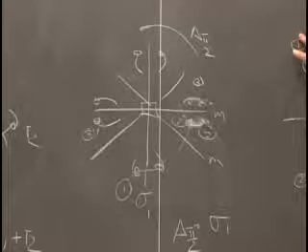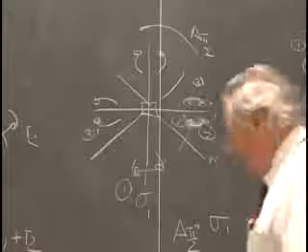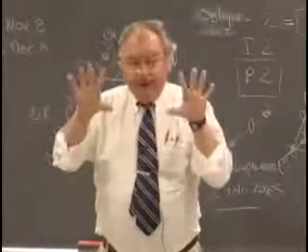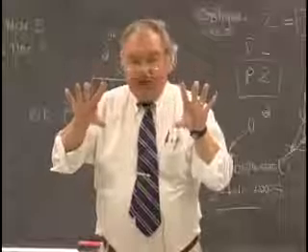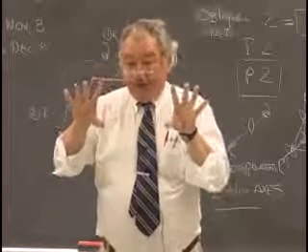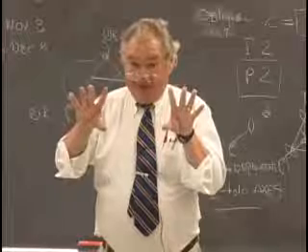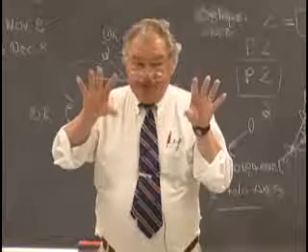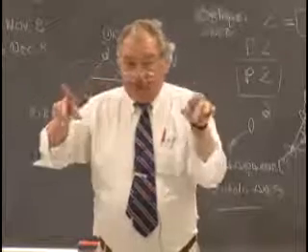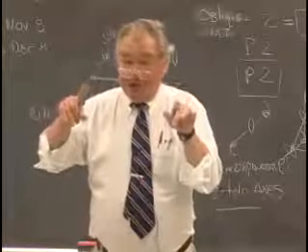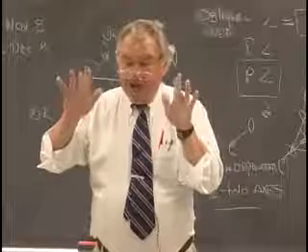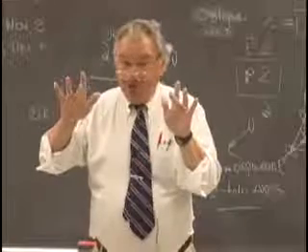So how can you tell? It's a very difficult thing to prove that this is the case, but you can interchange the order of operations when the two symmetry operations that are involved leave each other untransformed. And if the two symmetry operations move one another, then changing the order changes the net result. It doesn't change the nature of the operation, but it does change the locus about which it operates.